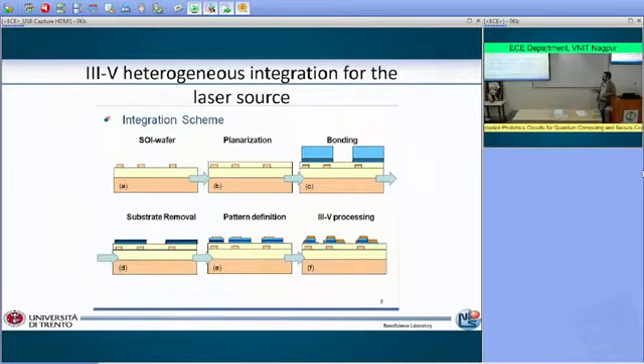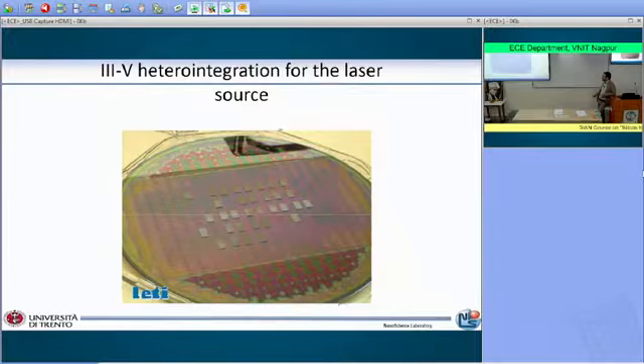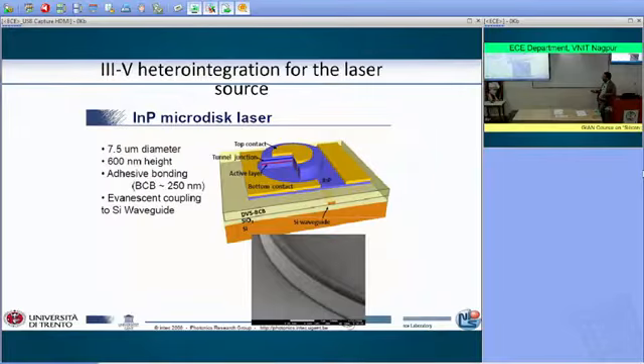And so once we have done that, you can do the usual 3-5 processing. So here is the scheme. You start with your SOI wafer, you planarize, you bond, and then you remove the substrate of the 3-5 semiconductor, and then you process the 3-5 semiconductor in order to make the laser. And the outcome is quite successful. Here is an example of one of those. This image is coming from Leti, which is a silicon foundry in Grenoble in France. What you see here are all the pieces of 3-5 semiconductor that have been bonded on top of the silicon. And then you can make the kind of laser that you want. Here is an example of a microdisc indium phosphide laser that is working very well. And this is also in 2018.